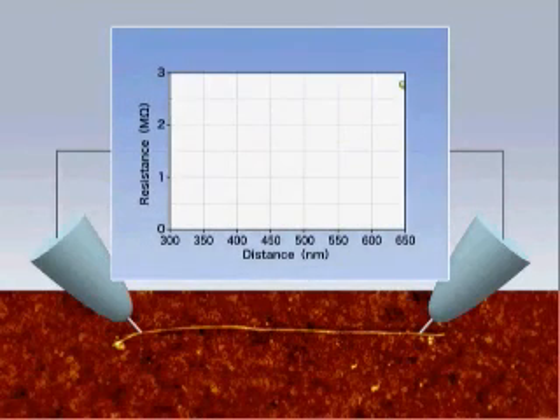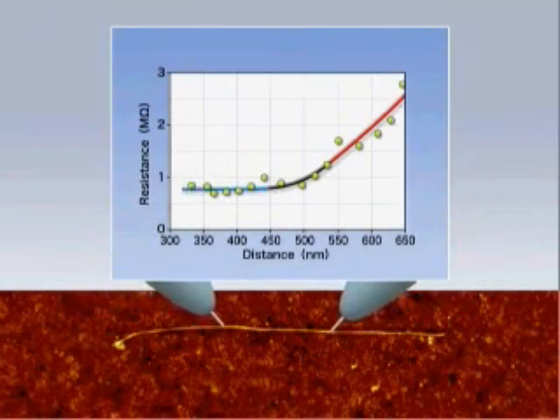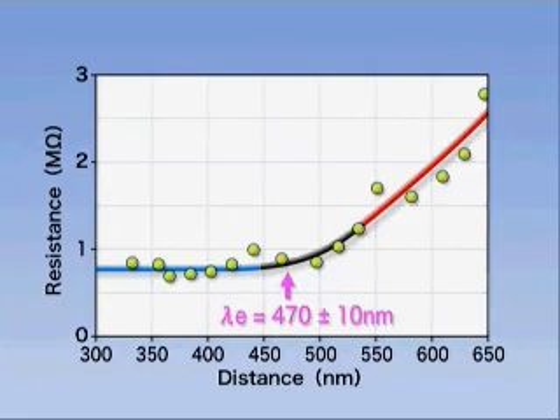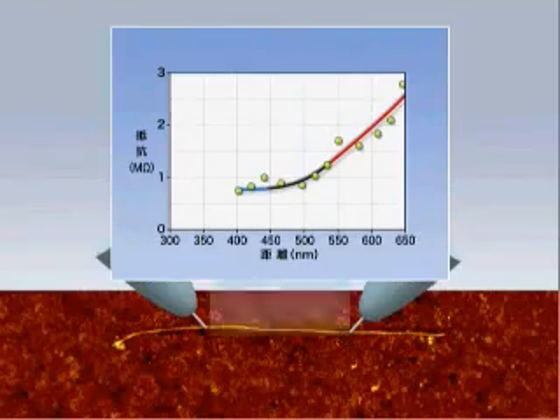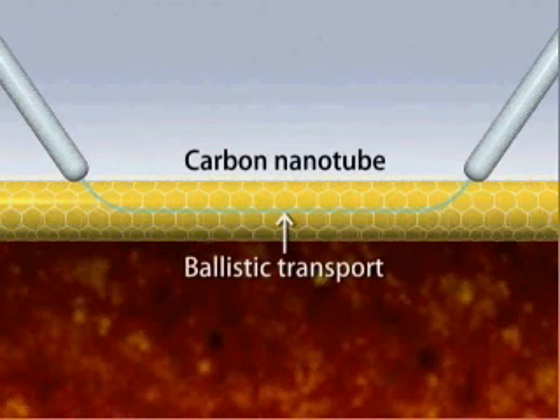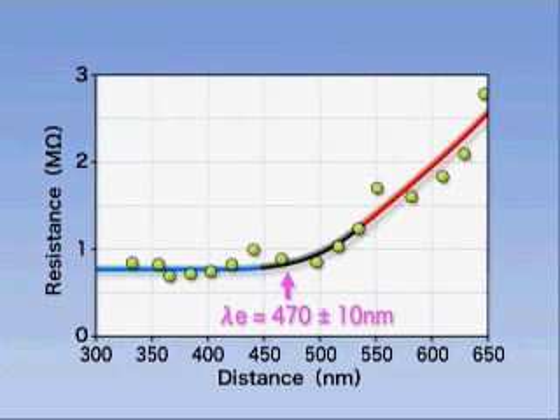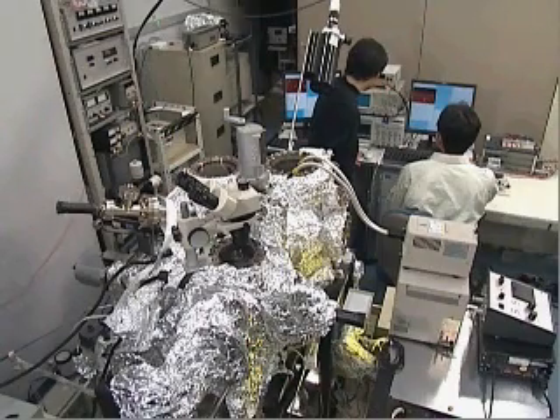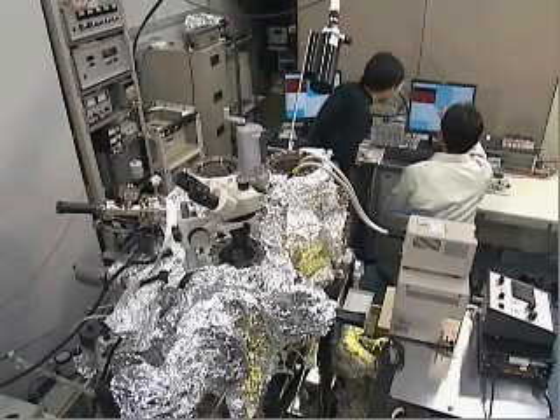However, measurements show that electrical resistance definitely becomes smaller as the distance decreases, but that under 470 nanometers, electrical resistance is the same. So, what is happening here? Under a certain distance, they observed ballistic conduction in which there is no scattering of electrons. In the graph, there is still a resistance value because of contact resistance with the measuring instrument, but the actual internal electrical resistance is essentially zero. In this way, the research group successfully observed ballistic conduction in a carbon nanotube and accurately measured the electric conductivities of various nanowires.